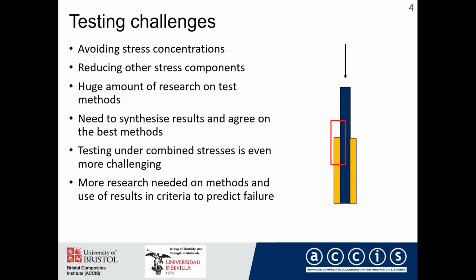There are a lot of challenges in testing composites. Clearly, avoiding stress concentrations and reducing other stress components are obvious ones. And there's been absolutely a huge amount of research on test methods. But I think there's a need to try to synthesize that and to come up with best methods. Despite all the work that's been done by thousands of researchers and all the committees, the ASTM and other international committees, I think there's still a need for more work to synthesize and really appreciate the results of all this work that's been done and try to reach agreement on which are the best methods to use. And of course, testing under combined stresses is even more challenging. And there's clearly a need for more research on the methods and also on what we do with the results, how we use them in criteria to predict failure.